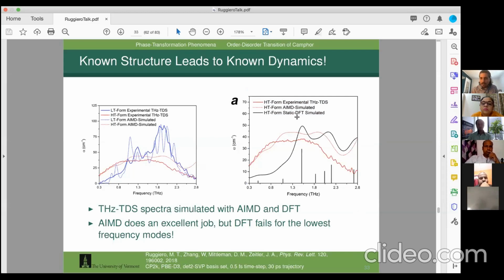What was interesting to us is the higher in frequency we went, things started to agree between the two methods. But at low frequencies, even though there are some peaks predicted from the static DFT, they're not the same intensity as the molecular dynamics.